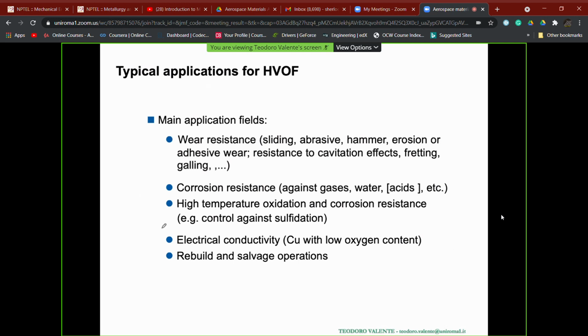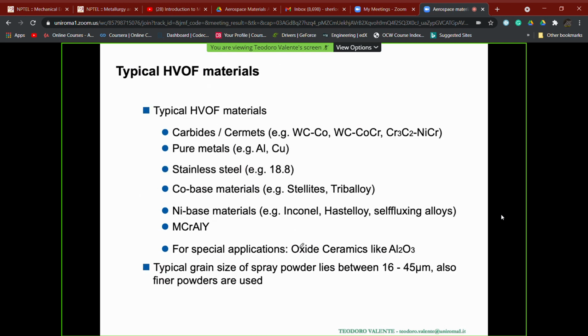In some cases, we can use HVOF also in order to fabricate coatings with proper electrical conductivity. In this case, we are not going to use the powders that we have mentioned before. We are going to use copper, but we need to assure a very, very low oxygen content in the coatings. Otherwise, the electrical conductivity of the coating itself will fall in a significant way. Here you have a list of the most common. Then I will leave you also a more detailed table, but just to summarize, the most common and most typical materials used for HVOF.